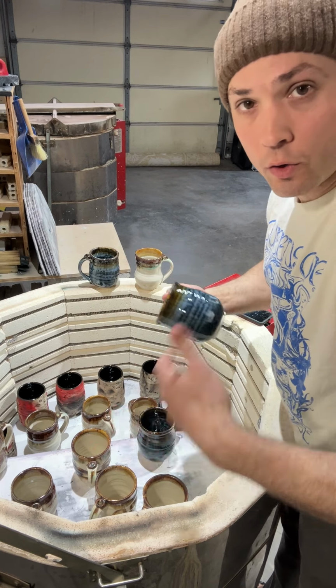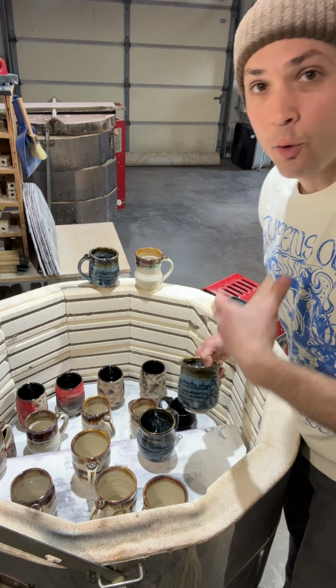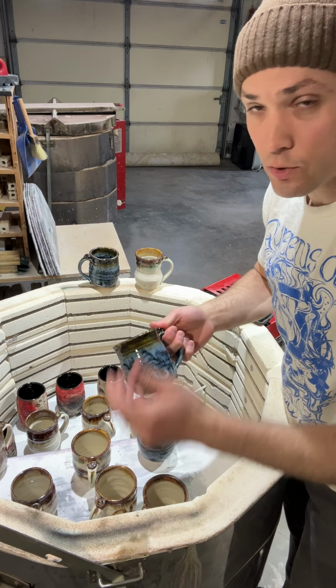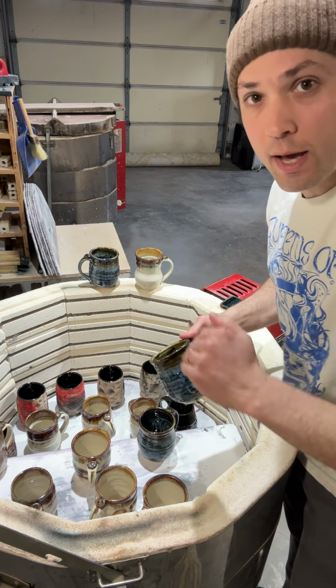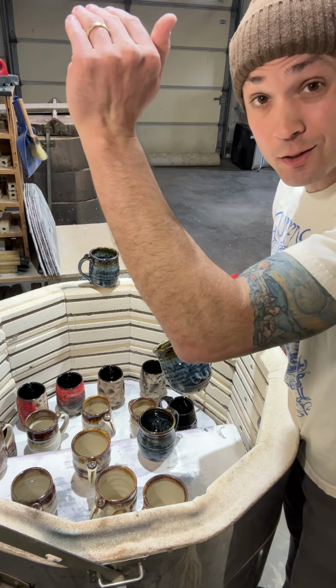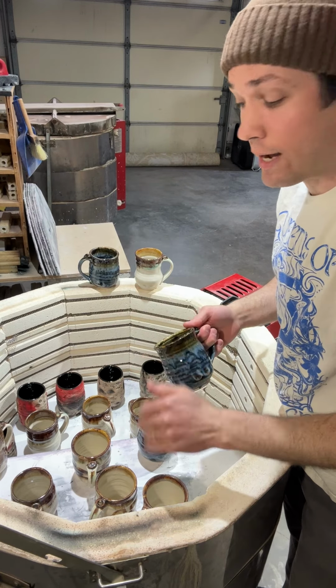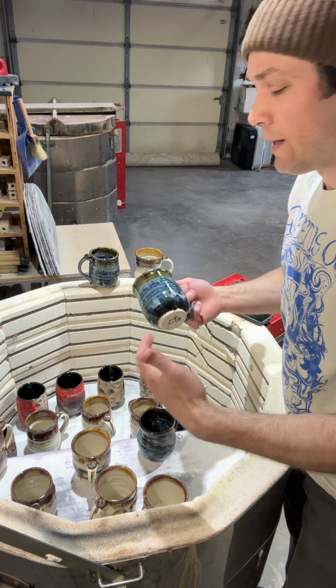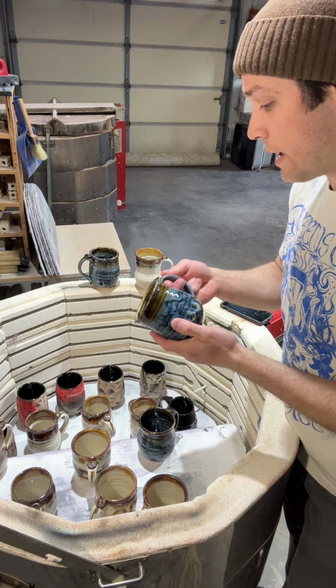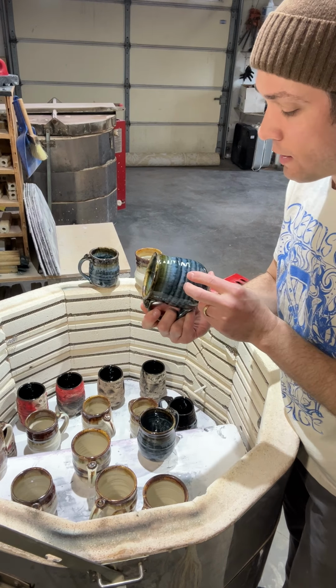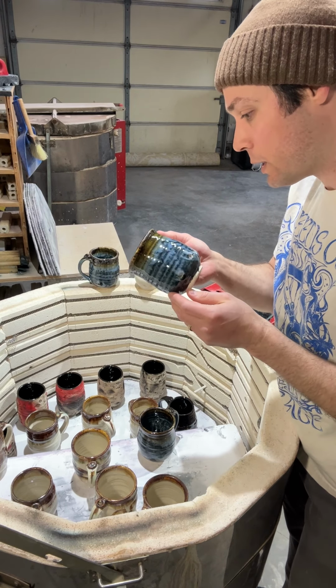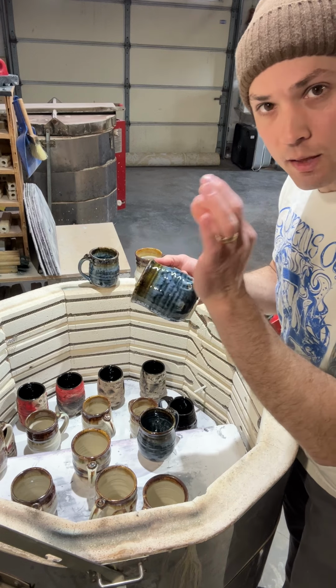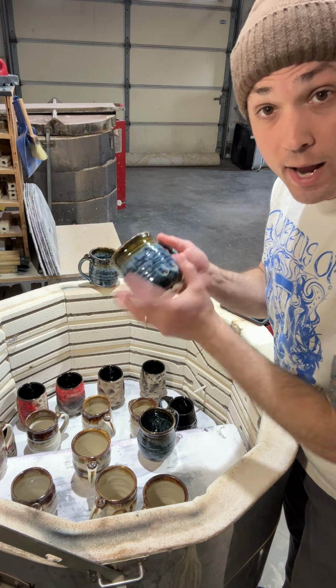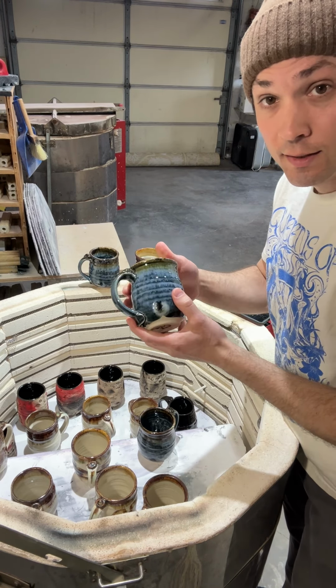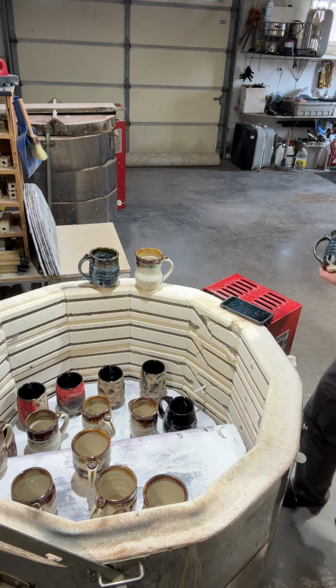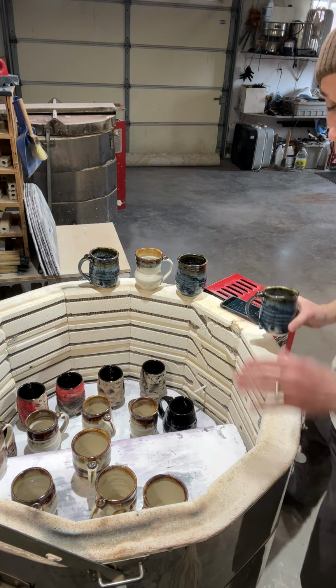Pots tend to get darker when you refire them, and you can refire them 4, 5, 6 times, but eventually they'll start to crack if you continue to do that as they go up and down to 2,200 degrees Fahrenheit and back down. But 3 firings, I found no difference in durability. Just like I said, the bubbling in the glaze that can happen, but that's why I added this glaze, and they look awesome.